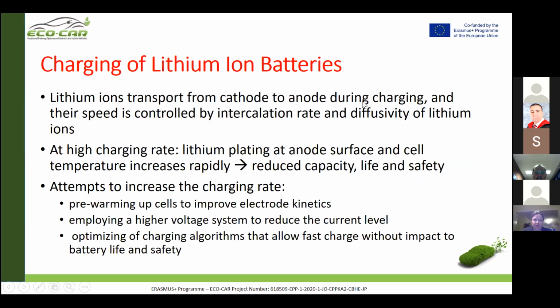So lithium ions are transferred from cathode to anode during charging, and their speed is controlled, of course, by the intercalation rate and the diffusivity of the lithium ions. If I have a high charging rate, the lithium plating at the anode surface takes place, and the cell temperature increases rapidly. If you feel that your lithium battery is getting very hot, then it's not a good sign. That means that some degradation is taking place.